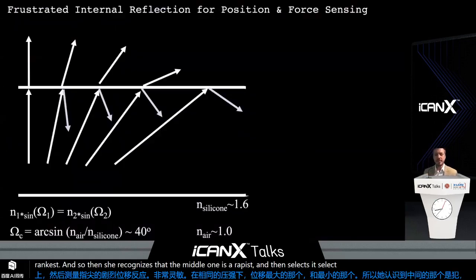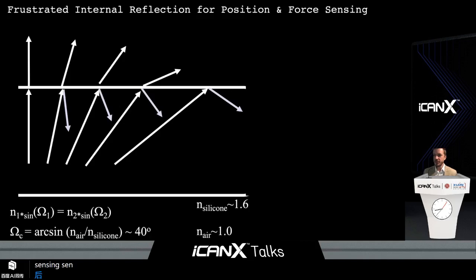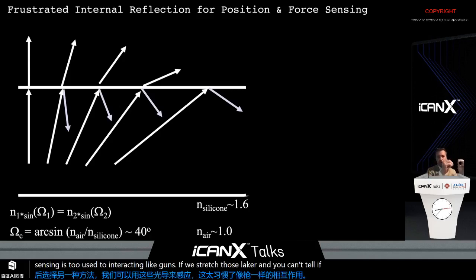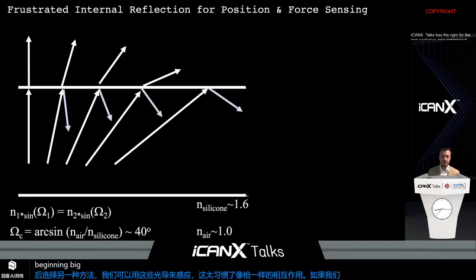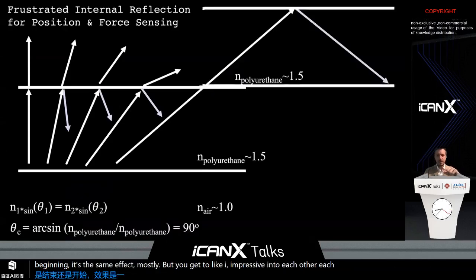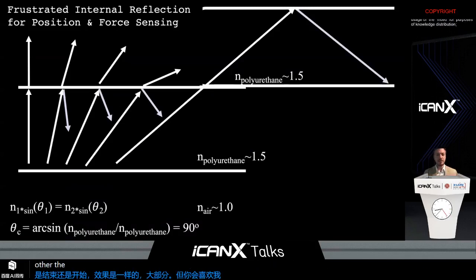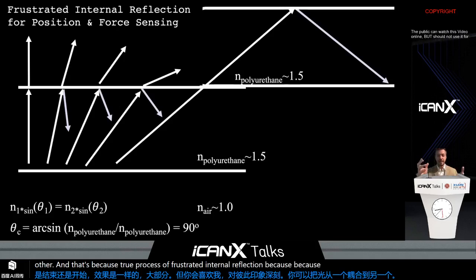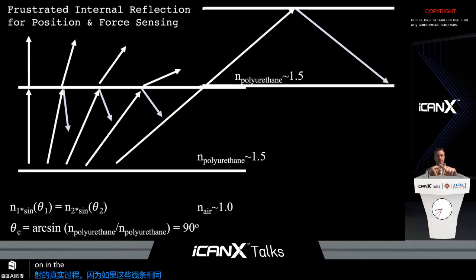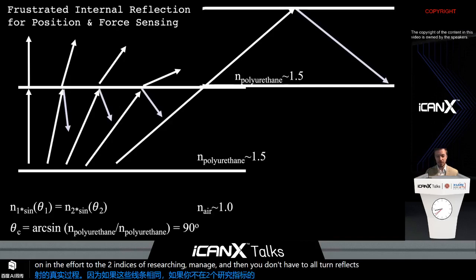Another way we can use these light guides for sensing is to use 2 interacting light guides. If I stretch one of those light guides, you can't tell if you're stretching in the middle or the end or the beginning. It's mostly the same effect. But if you have 2 light guides and press them into each other, then you can couple light from one into the other. That's through a process of frustrated internal reflection: if you don't put the cladding on them, then the two indices of refraction match, you don't have total internal reflection, and light goes from one into the other.